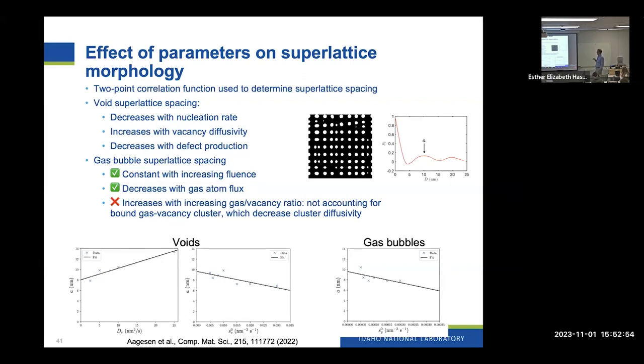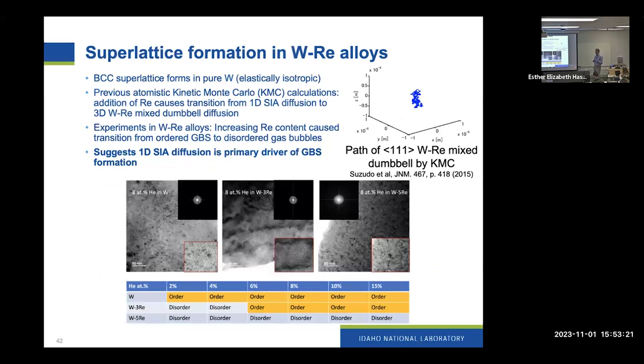The one thing that we didn't quite get right was as we increased the gas to vacancy ratio, we predicted the opposite trend as seen in experiments. And this was because we weren't accounting for the fact that when gases and vacancies are present in appreciable concentrations, they like to bind together, which actually decreases the diffusivity of the clusters quite a bit.